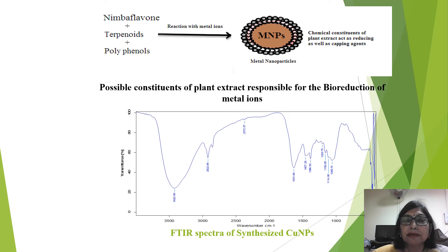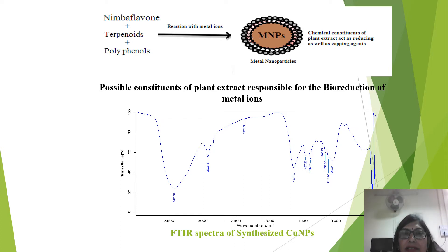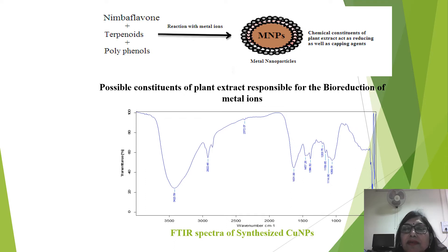The biomarkers present in the plant extract of Azadirachta indica, such as flavonoids, terpenoids, and phenolic compounds, act as a reducing agent as well as a capping agent in the formation of the nanoparticles. These biomarkers present in the plant extract are confirmed by the FTIR spectrum of the nanoparticles.